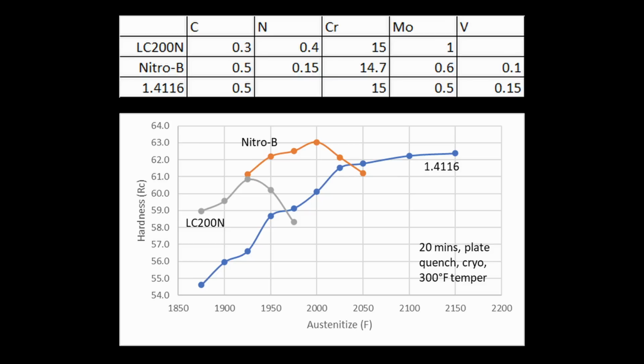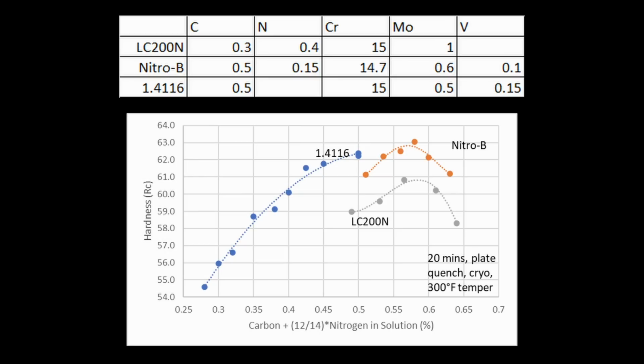But I always blamed that on the fact that they have high chromium in solution, which also drops the martensite start temperature and makes you have more retained austenite. And that's what gives them more corrosion resistance, all that chromium in solution. But Nitro-B has just as much chromium in solution as LC200N, but it's getting 2 points harder. So I used Thermo-Calc again and plotted out the carbon plus nitrogen, and the LC200N is getting just as much carbon plus nitrogen in solution as the Nitro-B. It's just that the nitrogen is not raising the hardness as much as a higher ratio of carbon would.